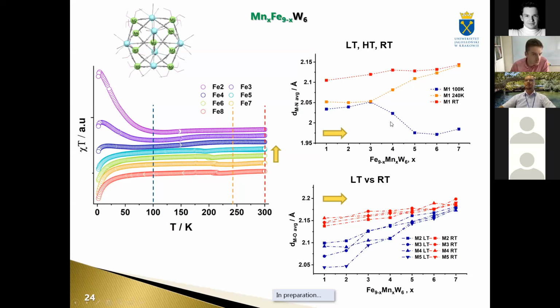Comparing the magnetic data with structural data, we can see. I would like to draw your attention to the central part at 100K in the iron-rich phases. So here we have iron-3. And these are the bond lengths which are characteristic definitely for iron-3 in these clusters.